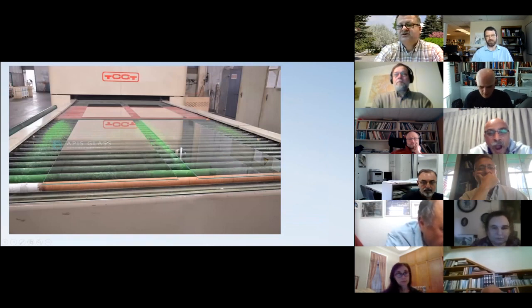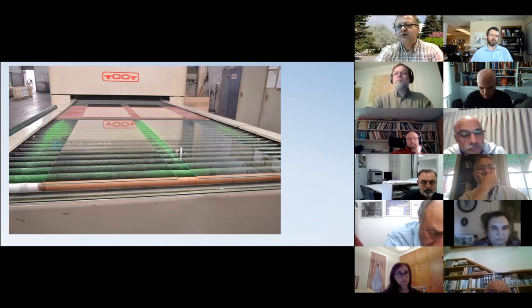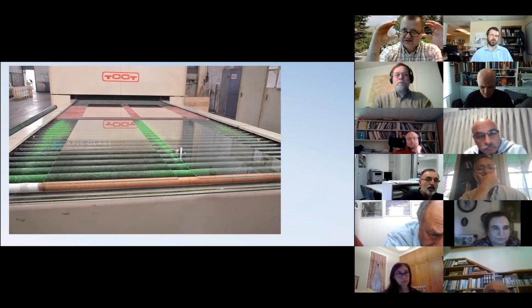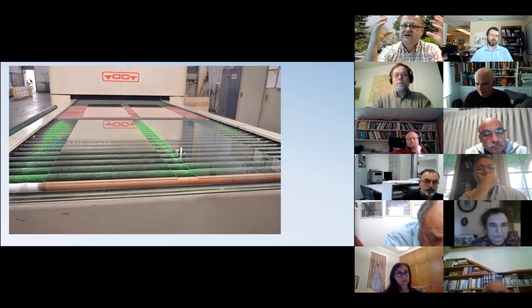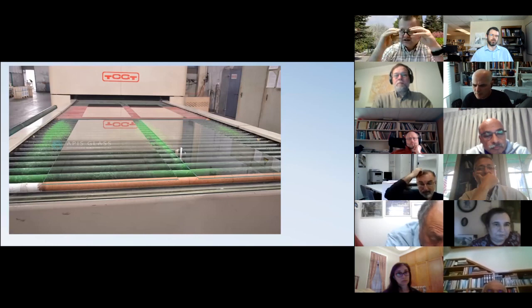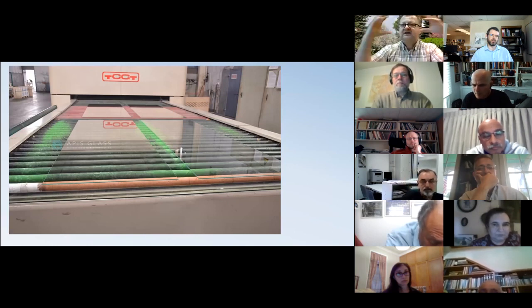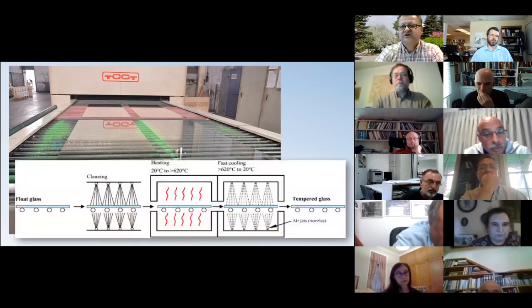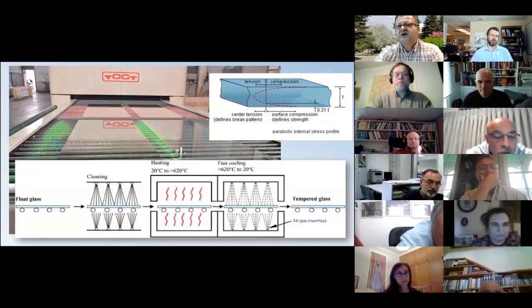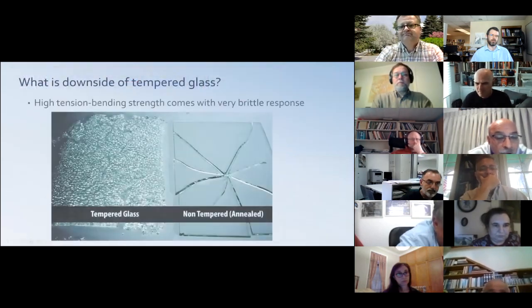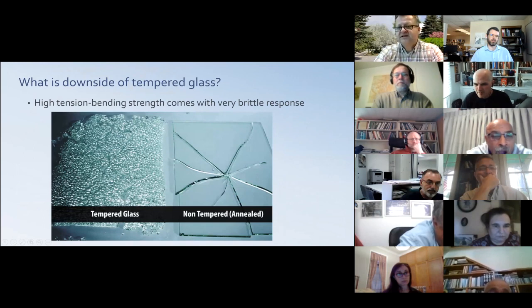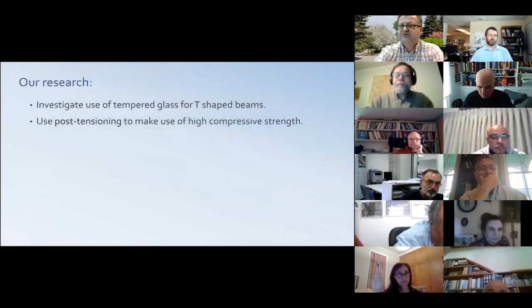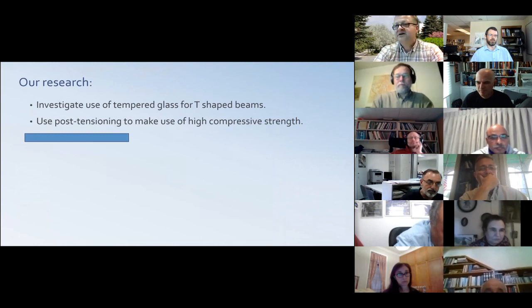So how it is done is you put the glass through some heating chamber, and when it comes out, you immediately cool it off. So the exterior parts are very quickly strengthened, or let's say hardened, and the inner part is still soft. And over time, as the inner part gets stiff, it shrinks and it applies a post-tensioning to the outer edge. So this is the production sequence. In this study, we have studied the regular glass on the right and tempered glass on the left. And I will present you the results that we have obtained, which were quite promising.